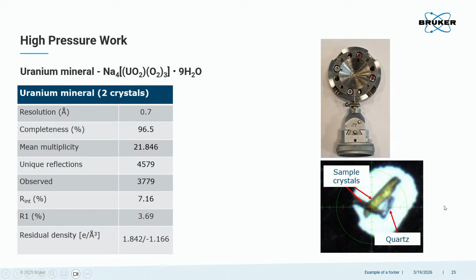More traditional single crystal high pressure work. Uranium. Well, there's an absorber. And what people also like to do now is to have two samples in the high pressure cell. For single crystal, it's actually really perfect almost, because our beam has just the right size to shoot through the aperture but hit both crystals. So we can treat that as a two-domain problem, which then also increases our completeness and also our multiplicity, because we just have more observations by looking at more samples at the same time.